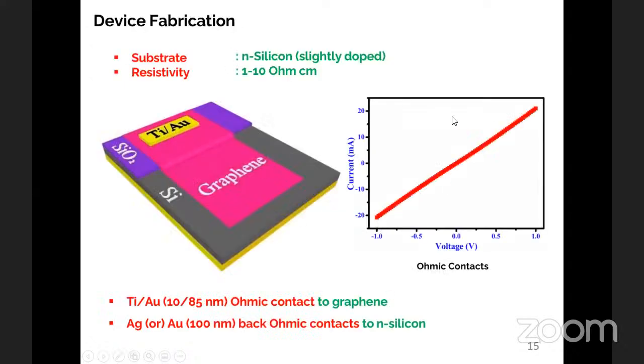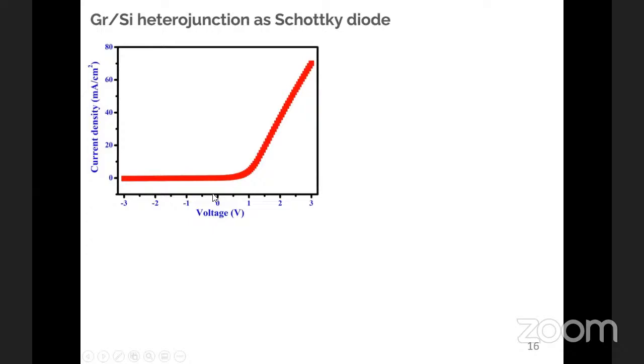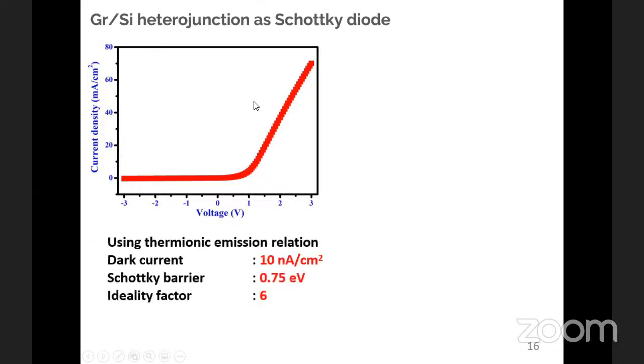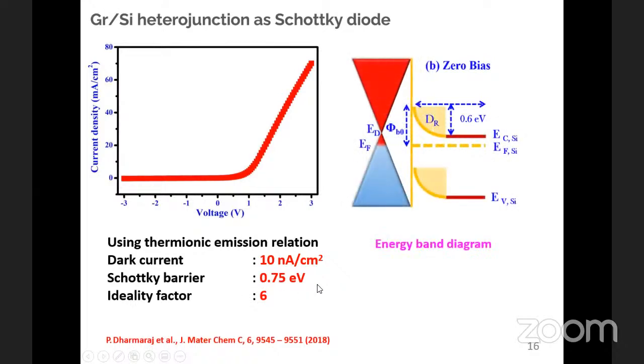This is the electrical curve for Ti/Au and graphene, as well as gold and silicon, but not for graphene and silicon. Here, this is the IV characteristics of graphene and silicon. It completely reveals the rectification behavior, which means it behaves as a Schottky diode, with a rectification ratio close to 500 or thousands, I forgot the exact value, but it is a high rectification value. You can see clearly that there is no current under reverse bias, and under forward bias you can see an increase in the current. That means these are perfect Schottky diode characteristics. Based on the thermionic emission relations, as well as the dark current value, I calculated the Schottky barrier height, which is around 0.75 electron volt.